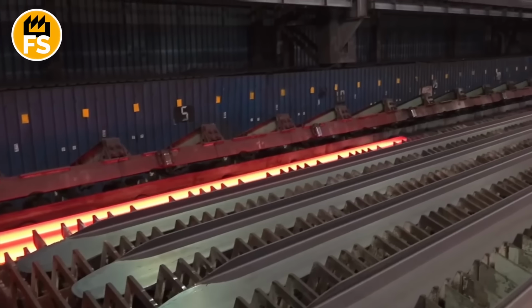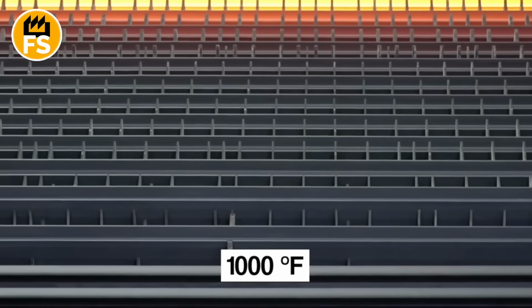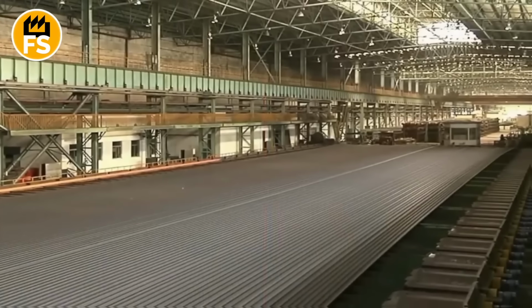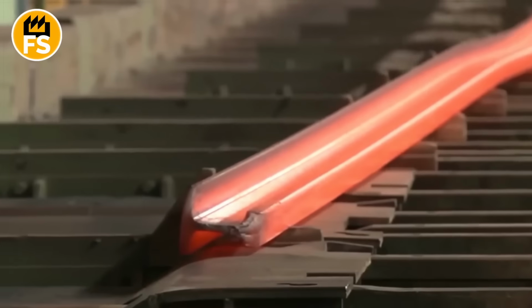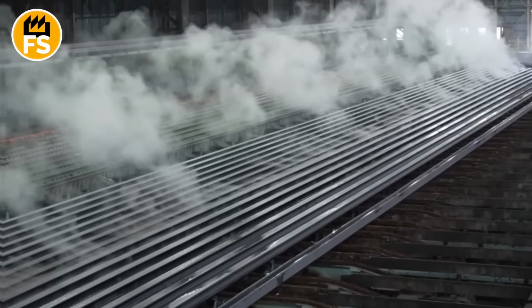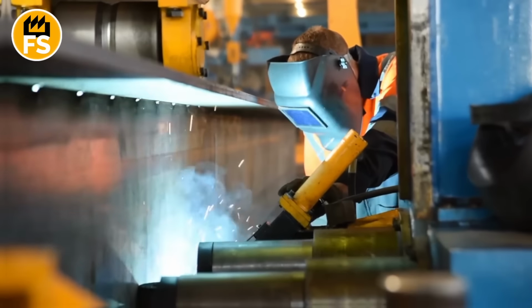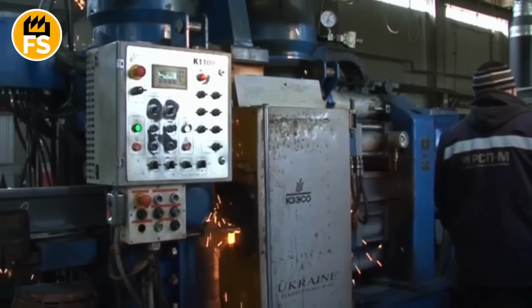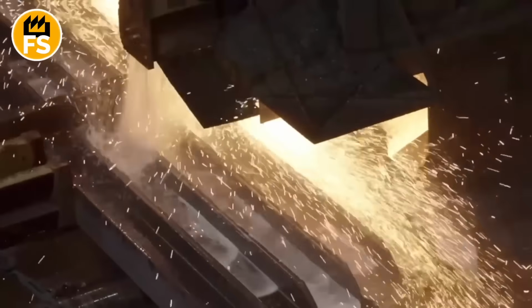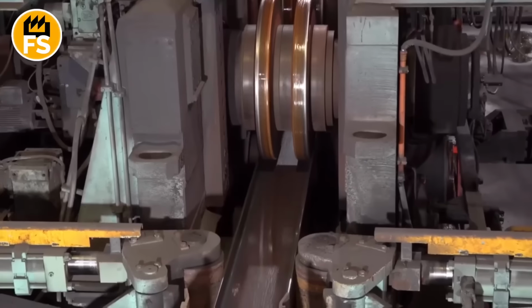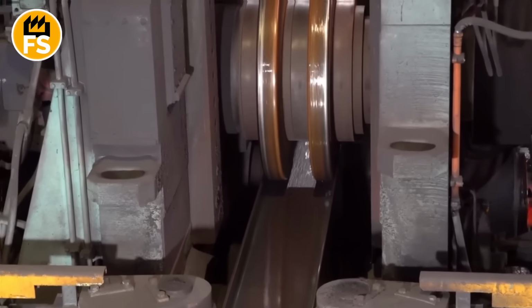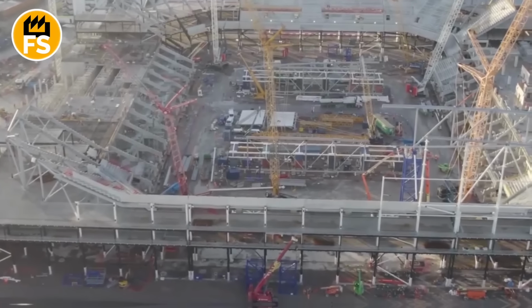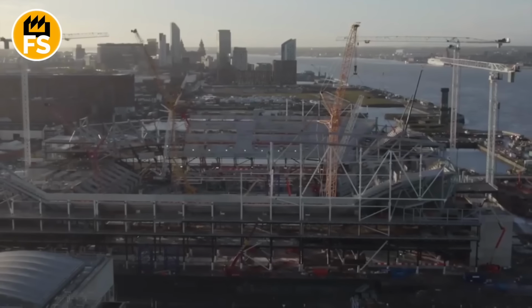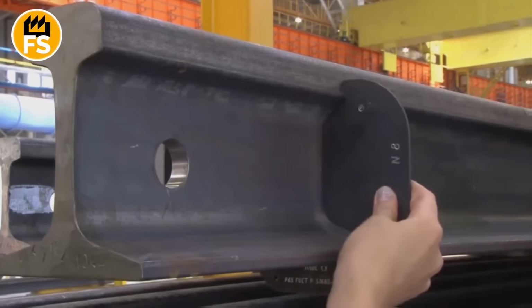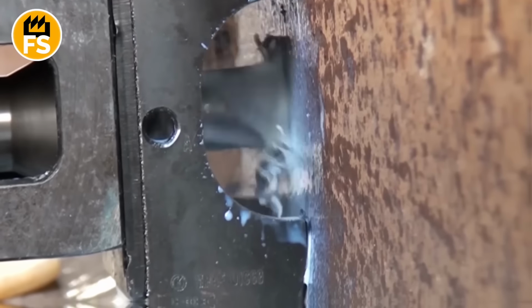After the beams come out of the rolling mill, they're still around 1,000 degrees Fahrenheit, so they go through a controlled cooling process where they're laid out on cooling beds and air-cooled down to room temperature over the course of several hours. Once they're cool, each beam goes to the fabrication area where they get cut to exact lengths using massive saws with carbide-tipped blades, and this is where the beams start being customized for their specific locations in the stadium. For a project like SoFi, every single beam has a unique set of holes that need to be drilled at precise locations for the bolts that will connect it to other beams.